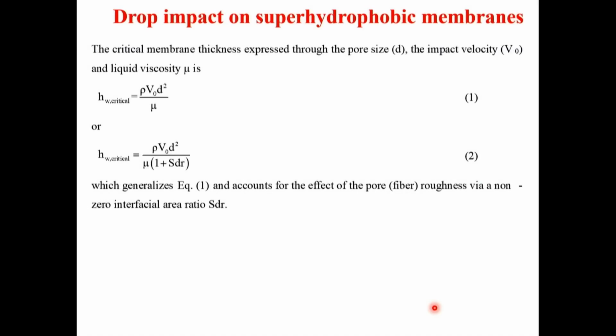So this is a direct proof that it exists, and that's how it works. So then the question is, if you cannot stop it by wettability, non-wettability, roughness, what about the effect of thickness? Indeed, you can easily calculate, and I'm skipping the calculation, that there is always a critical thickness, which is exactly the thickness where all this kinetic energy will dissipate by viscous forces, and there won't be any outflow from the membrane.